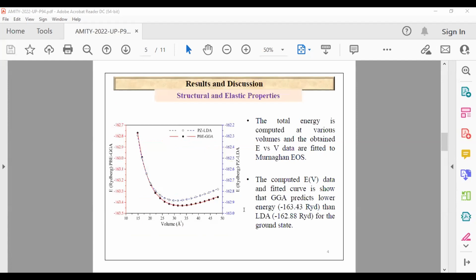So we come to results, and first we discuss the structural properties. When we vary the unit cell volume, this is a cubic structure, so there is only one lattice parameter that can be varied, which is lattice constant a. By changing the value of lattice constant, we change the volume, and we calculated the total energy at different values of volumes. The computed total energy versus volume curves are shown in this figure, and we can see that the curve corresponding to GGA calculation has lower energy than the LDA calculation. So the generalized gradient approximation functional predicts lower energy than the local density approximation.